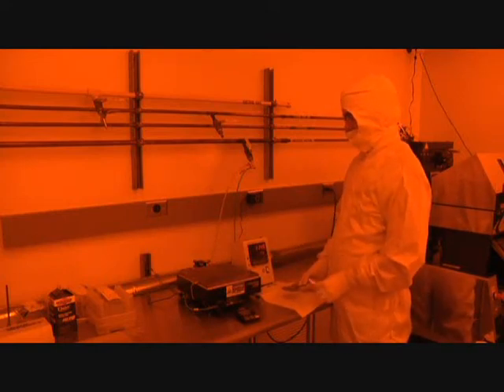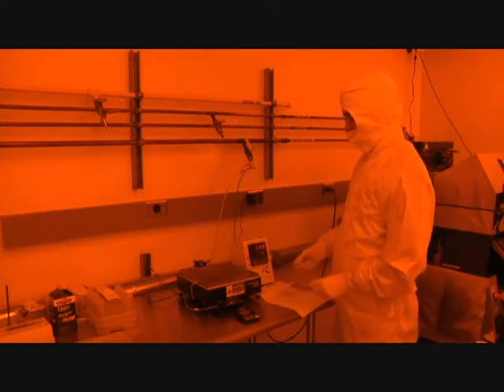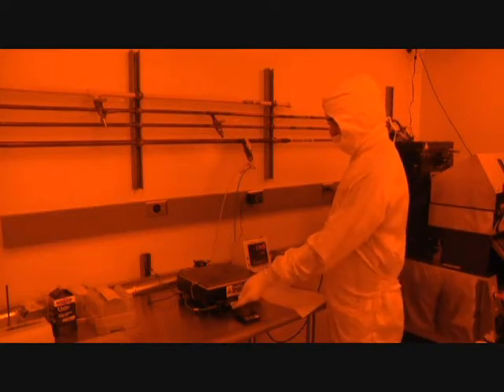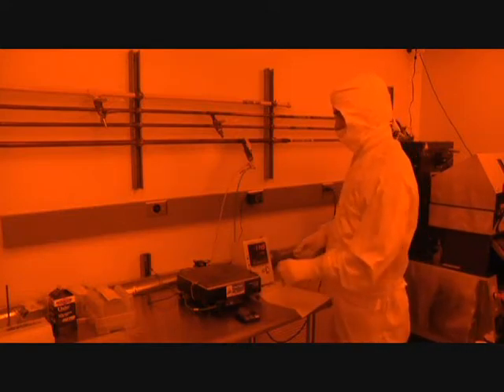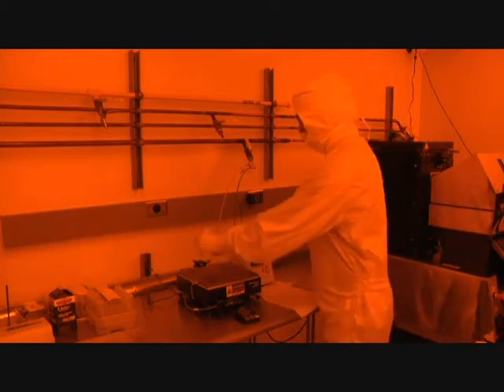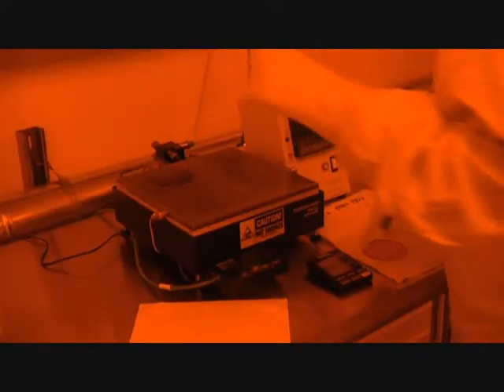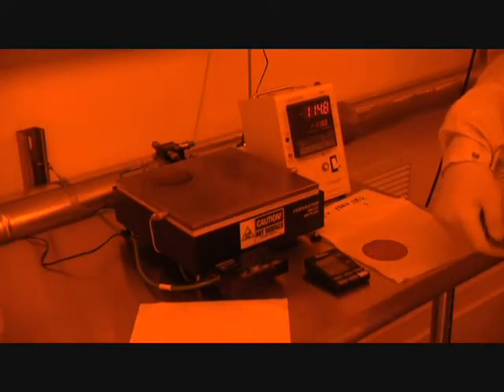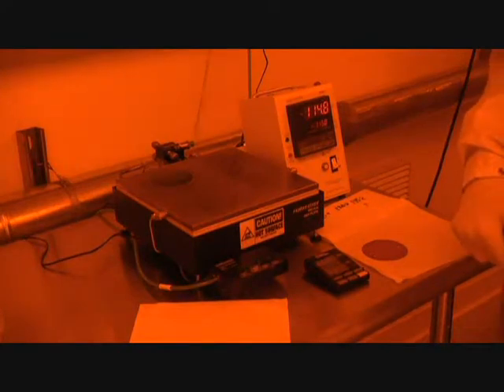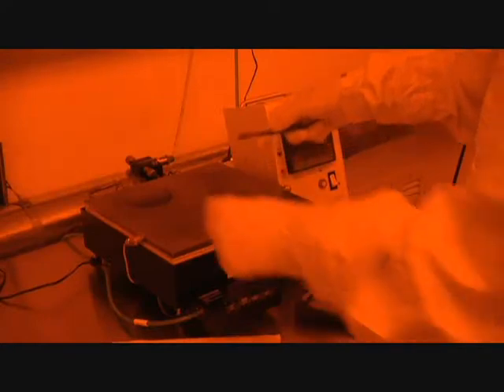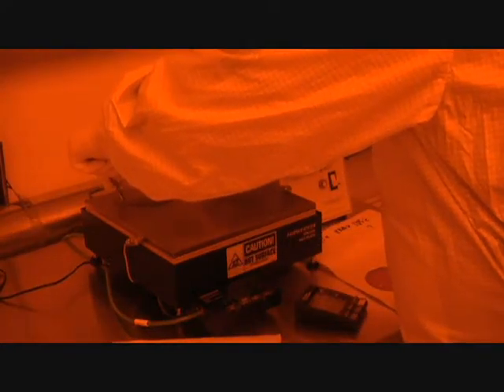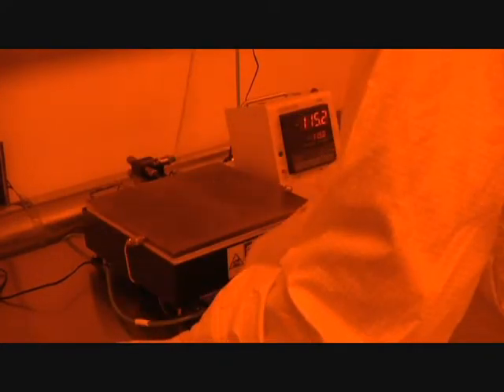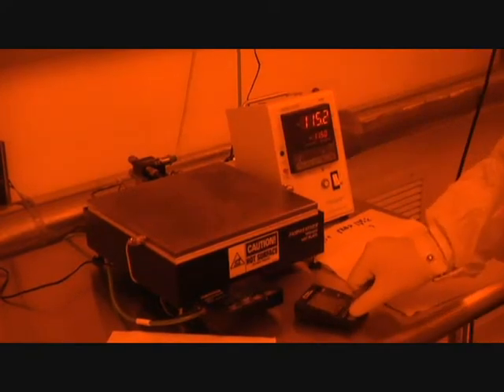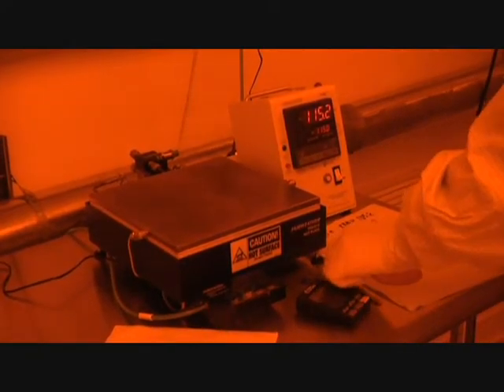And we're going to basically place the wafer on the hot plate. We've got vacuum chucks on this hot plate to hold the wafer down and get a nice uniform bake. And we're going to bake for 1 minute at 115 C. Now the bake is complete.